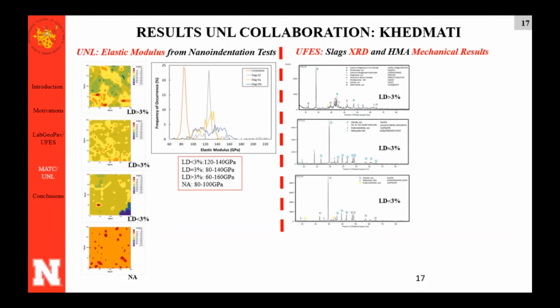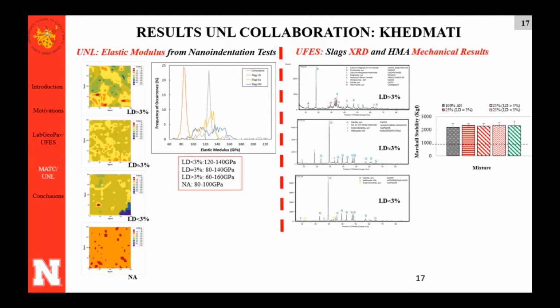So we saw that in general, with the level of expansion, the average elastic modulus didn't change much. And comparing with the natural aggregate, it increased. Natural aggregate, the average is around 90 gigapascal and slags around 130. So it's a little bit higher. But this difference maybe is not that considerable when you think about the mechanical performance of your asphalt concrete. And maybe that's why we didn't have much change here. The elastic modulus indeed increased a little bit, but this increase was not significant when we added this material at 25 and 50% on the Marshall stability.